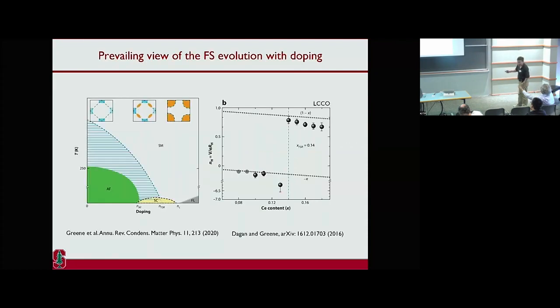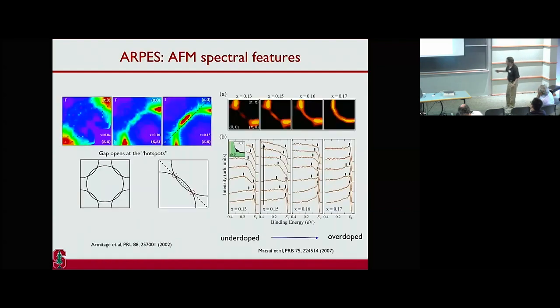Now, which doping was that? That's about some 15% doping. Okay. Eventually, the other one merges. So that's in this doping region. You can see that this is well accepted, that there's a crossover from a reconstructed smaller Fermi surface to a larger Fermi surface in the literature. In fact, this kind of physics is already there in Peter Armitage's thesis work, and you can see the hotspot, and that's 2 decades ago, and that's widely seen in the literature.